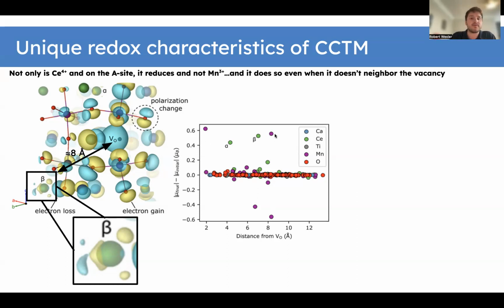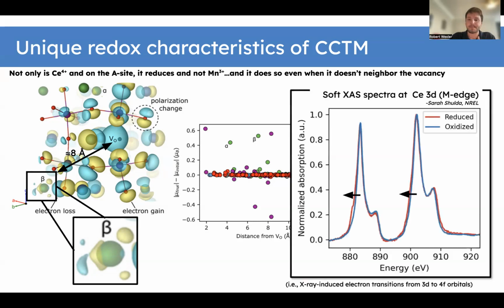However, 2 ceria reduce far away from the vacancy. The one that reduces the most is actually almost 8 angstroms away. And this idea that the manganese on the B site sublattice doesn't really undergo redox on average, and the fact that cerium does on average reduce, is shown in soft XAS spectra done by Sarah Shuida at NREL. So looking at the Ce M edge, you can actually see a reduction in the binding energy of the electrons associated with the reduction of cerium.